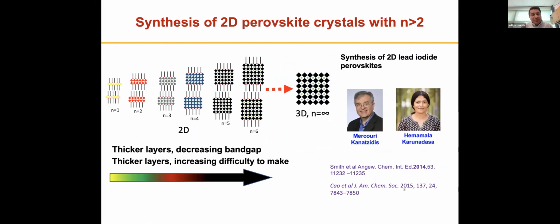All right, so if you think about the synthesis of this, then there was some really nice work done by Mercouri Kanatzidis and Hemamala Karunadasa. Just around the time when people were interested in the 3D perovskites, these two groups demonstrated that you can actually grow a series of these types of perovskites, which have these different N values, and you can really control them. So for example, here I'm showing you a series which goes from N1 to N6. And you can see that through solution processing, you can very nicely control the number of layers that you have. And you can go all the way to 6.